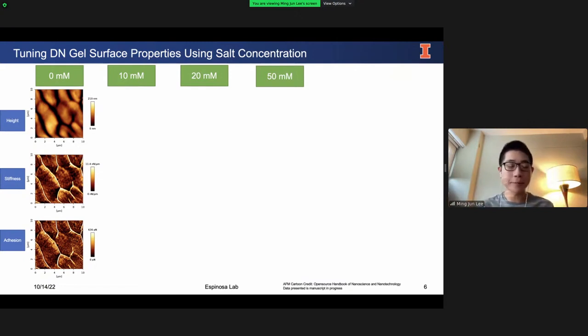the agarose network. And one reason why I believe this structure appears is that if you look in the second image in the stiffness channel, the valley regions correspond to a higher level of stiffness. And through common knowledge in hydrogel space, we know that agarose is the more brittle and more stiff network compared to the copolymer. So this is why I believe there are heterogeneities in the surface structure. The elevated sides are the copolymer, whereas the lower height is the agarose network.